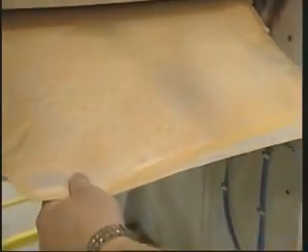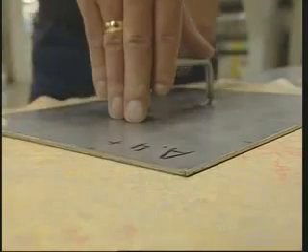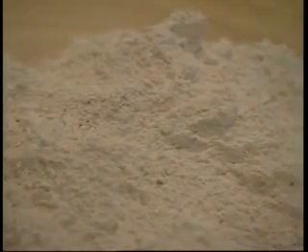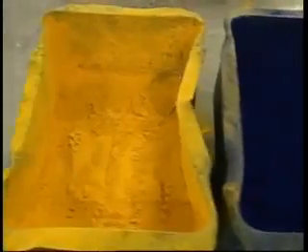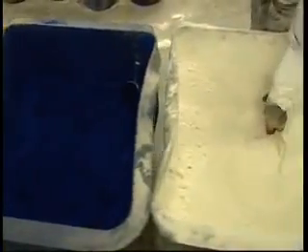Before a color is added, it is manufactured in the sample factory. The linoleum pattern slates made here show what the material will soon look like. In order to actually manufacture this, we return to our linoleum cement, which is now ready for further processing. First, ground limestone is added to the ochre-colored cement, making it dry. Then, wood flour is added. Finally, various natural pigments are added, which eventually give the linoleum cement a deep, warm color. The effect is astonishing.